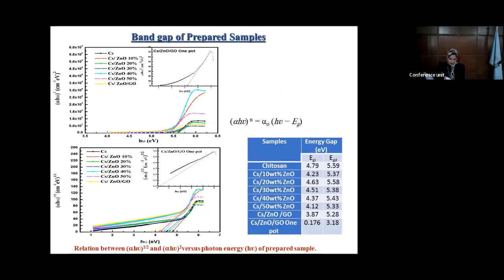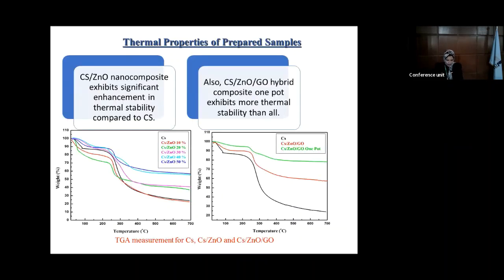Values of both direct and indirect band gap are calculated also, as seen with increasing the filler. The value of direct and indirect band gap energy decreased compared to pure chitosan, and it was a lower value for chitosan doped with zinc oxide and graphene oxide. Previous results showed that the chitosan zinc oxide graphene oxide prepared using the one-pot hybrid method reduced the order and is the best preparation method for the use of chitosan zinc oxide graphene oxide as optoelectronic material. Also, thermal gravimetric analysis was conducted to study the thermal behavior of the prepared samples.